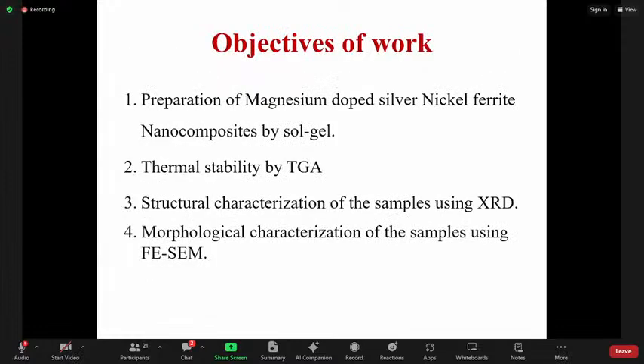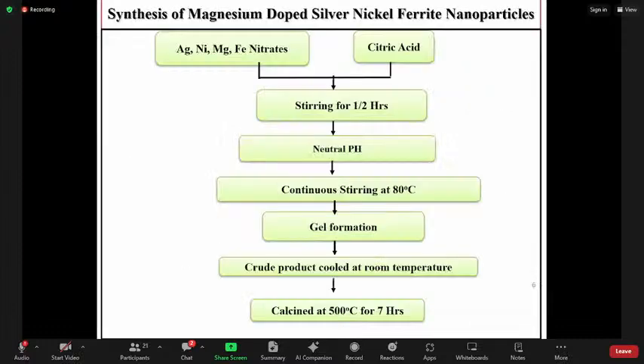The first is preparation and characterization. So this is the important part of the synthesis. Firstly, I have taken the nitrates of silver, nickel, magnesium, and iron. I have taken this with citric acid. Then stirred it for half an hour. It all got dissolved. I have maintained the pH neutral at 7. After that, I have given continuous stirring at 80 degrees Celsius with the help of a thermometer. I have maintained the temperature. I got the formation of gel.